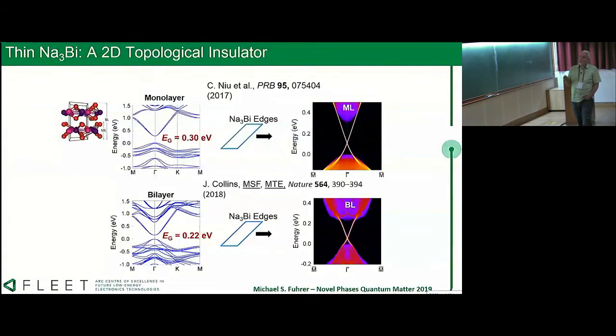So sodium-3 bismuth is the one we're interested in. I'm showing now some DFT results on monolayer and bilayer sodium-3 bismuth. If you make it very thin, these two materials are actually topological insulators with very large band gaps. Predicted band gaps on the order of 300 millivolts. And you can see edge states if you do the projection of the band structure onto the edge in monolayer and bilayer.